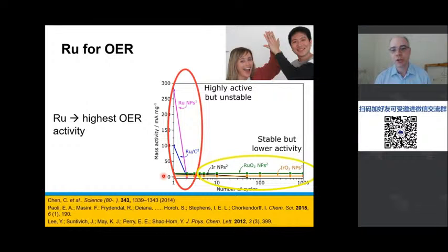And then your other kind of option is that you can use oxide catalysts. And the oxide catalysts are great. They're very, very stable, but they don't have anywhere near the activity that the ruthenium metal, oxidized ruthenium metal catalysts have. So we felt that there was a lot of empty space in this area here. So we wanted to try and see if we could make some catalysts that could start filling this empty space by being both active and hopefully have some stability for ruthenium metal.